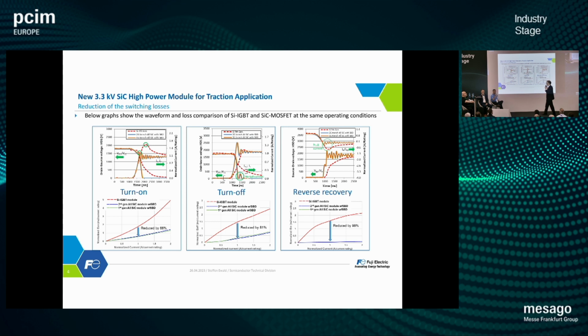So now we will look at some switching waveforms. On this side we have the turn-on waveform, the turn-off waveform, and the reverse recovery waveform. What we can see is smooth switching, there's not much ringing in the system. And the really interesting part, a bit difficult to read here, these are simulation results comparing the silicon module in the same package. In blue we have the silicon carbide module with our second generation trench MOSFETs, and the green graph is our first generation silicon carbide trench MOSFET. The reduction here for turn-on is 66%, for turn-off we are at 80%, and regarding reverse recovery, 98% reduction compared from silicon to a silicon carbide module.